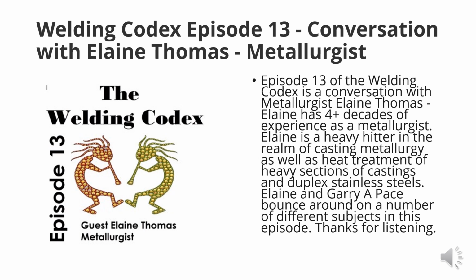Right. And I was going to say, too, when we'd qualify some of these welding procedures at the foundry, we'd use some 8 or 10-inch thick test coupons. I'd have a guy welding there for like a week straight. They'd run one weld pass, and then they'd sit there for 20 minutes. Because once these test coupons would get up to heat, this material doesn't have a very high coefficient of thermal conductivity. It's not like aluminum where it just sheds heat. It's the flip side, where this stuff just soaks it up and keeps it. That's interesting. I didn't really realize that. Yeah, so those guys would be over there for a week or so just welding and welding, and you're just like, dude, stop. If it gets above a certain temperature, which goes against everything they've been taught since junior high or vocational school.